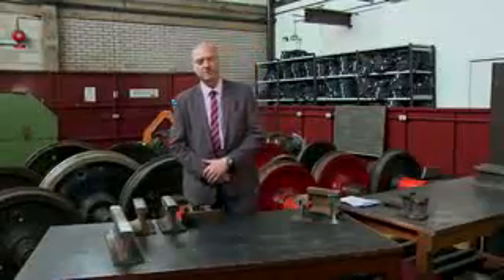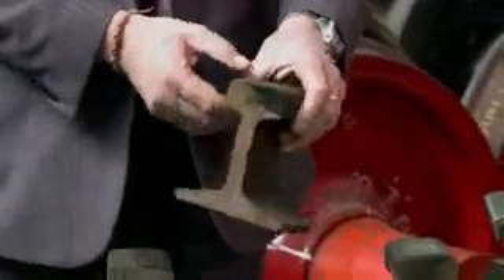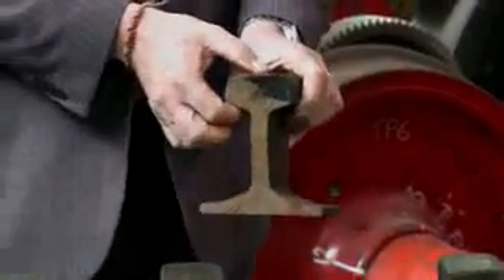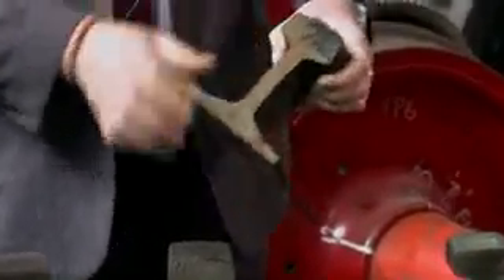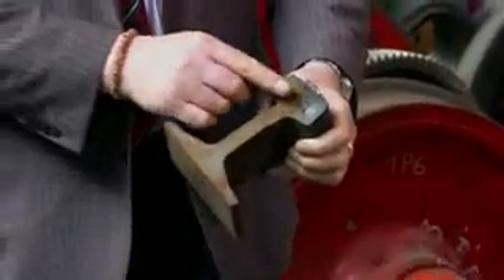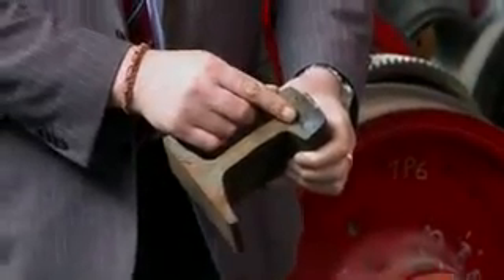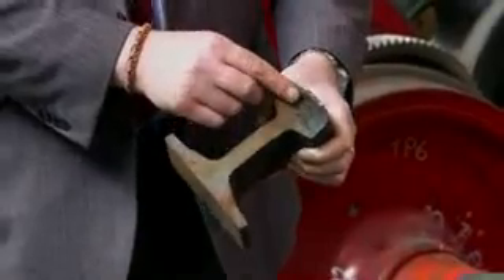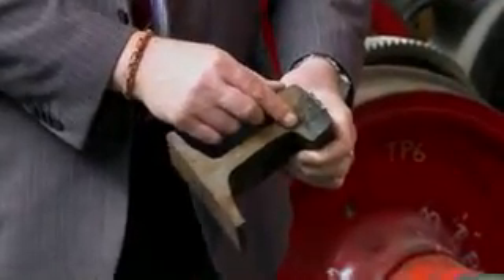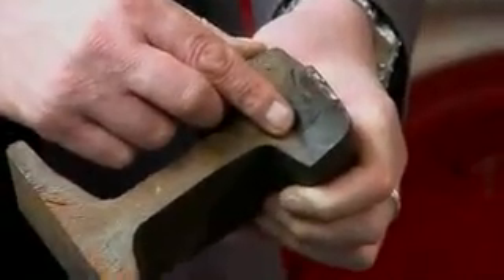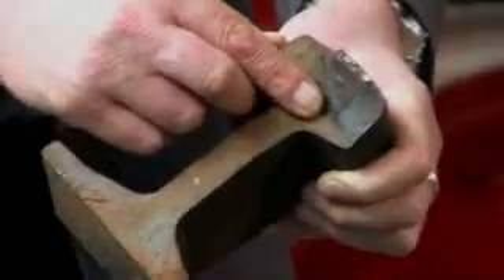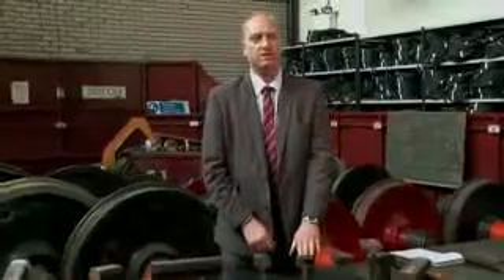There's a few examples of rail we have here. This sample here shows a fatigue crack which is initiated from the surface of the rail. It's caused by the repeated passage of wheels over the surface, which will initiate small cracks, and then through fatigue this will grow progressively over a long period of time. The discoloration and classic markings you can see here are a result of the surface becoming oxidised and corroded where it becomes exposed to the elements. Surface damage and rolling contact fatigue is our biggest cause of problems. It accounts for something like 50 to 60% of all defects we remove from track each year.